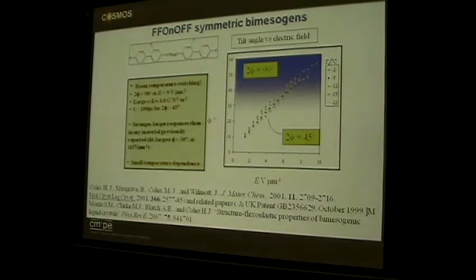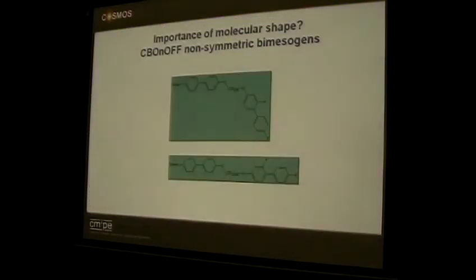And when you get this on the website, there are some of the references to these materials, and the last one there with Steve, where we reviewed what we've been doing with these bimesogenic materials, how we make mixtures that work at room temperature. What's important? The shape's important because you want to be able to bend and flex your materials. Okay, if you have odd and even members, something in liquid crystals is that as you add an extra CH2 group in a spacer, you kink the molecule and it will kink it back. And so it matters whether you have 9 or 10 carbons in these spacer chains.